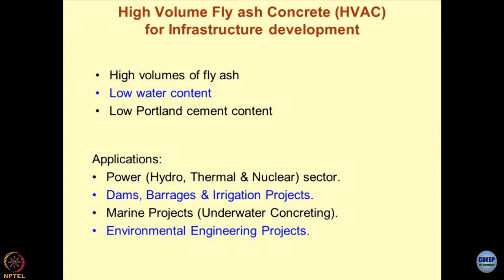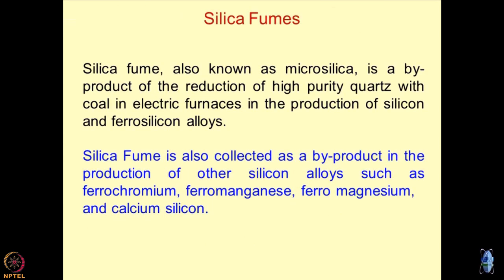The entire environment, because of the presence of acid-forming bacteria under anaerobic conditions, poses a big challenge — how do you protect your structures? Specialized environmental engineering projects require high volume fly ash concrete which is quite durable, including lining of tunnels through which water or sewage is flowing. Silica fume is another interesting man-made geomaterial and is a very high-end material used for creating concrete — extremely fine particles clog the pores of the concrete, and hence the concrete becomes highly durable.